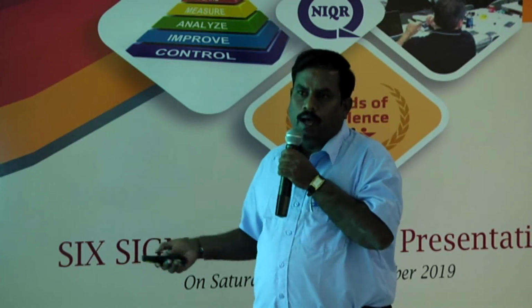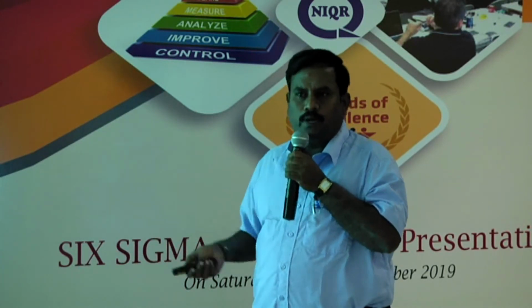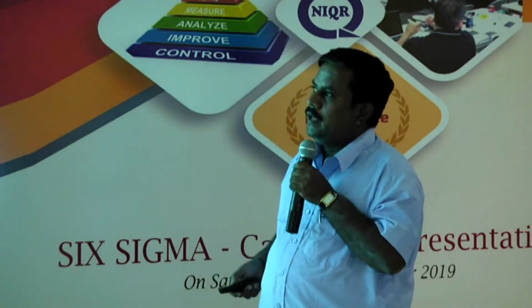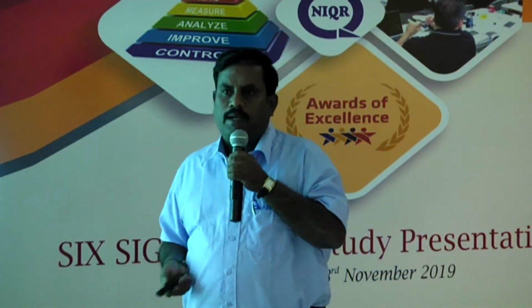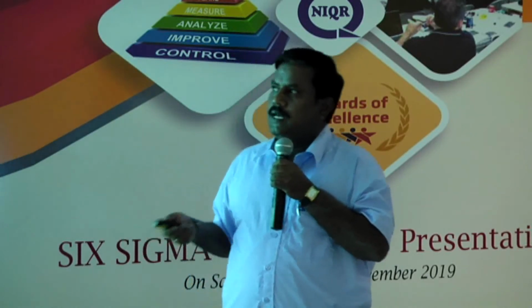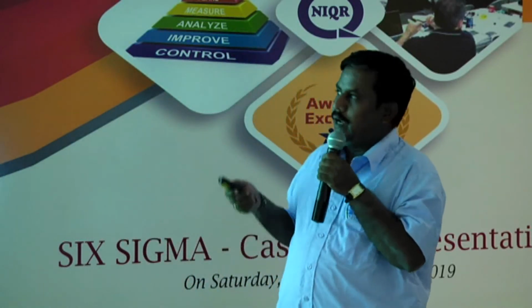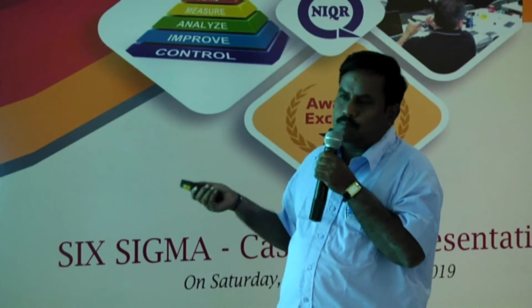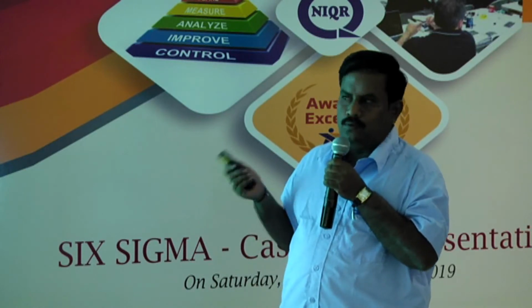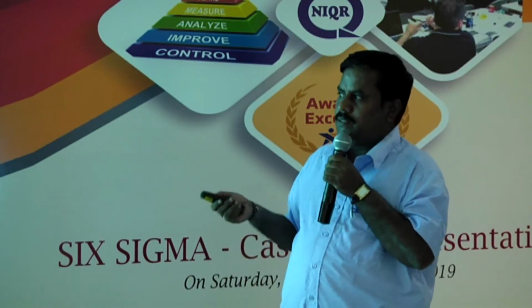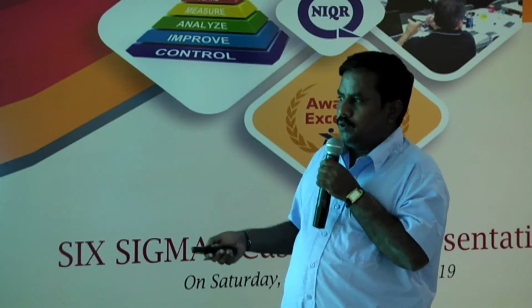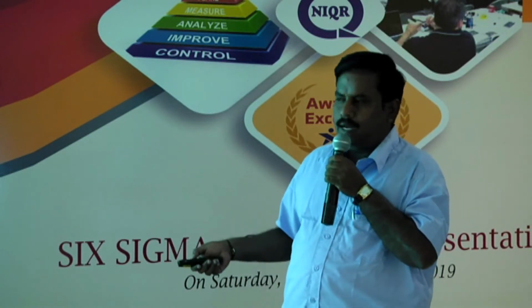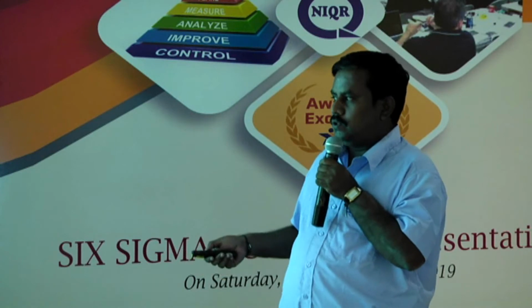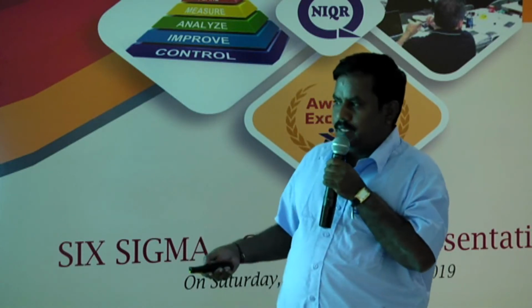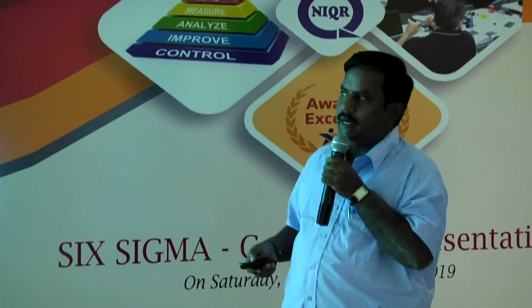There is hot air gas escaping during solidification. Then in our detecting tool, we used B versus C to validate the root cause. Since good and bad parts can be created alternately, we selected B versus C to validate the root cause. Designing the B versus C condition for the project, the tool used for finding the result is the rank comparison. Hence, B conditions are those corresponding to the good category and C conditions correspond to the bad condition.